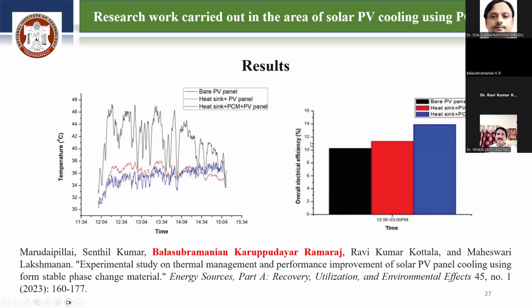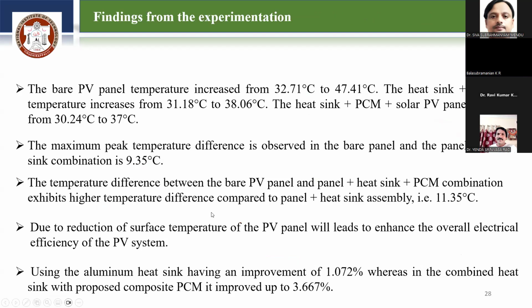Here on the right-hand side we can see the overall electrical efficiency of the bare PV panel, the heat sink with the PV panel, and the heat sink plus PCM adapted in the PV panel. For the bare PV panel, the electrical efficiency is around 10%. For including the heat sink at the bottom of the PV panel, another 1% rise we observe. And when we adopt the heat sink along with PCM, a further increment of about 2% is observed. So totally around 3% of electrical efficiency we achieved with the use of the heat sink and PCM. From the experimentation, these are all the findings.